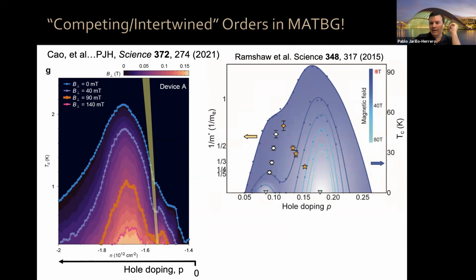In this case, they have to use gigantic magnetic fields, up to 80 Tesla, in order to measure this, but they basically saw a similar evolution with a small perturbation on the TC, which then isolates the 2 domes, and only one last remaining dome survives. Of course, the big difference between this data is that here the actual data points are those few discrete data points that you see here, okay? Whereas here, all of these data points are continuous measurements that we can take in this diagram, because we have full electronic control over our doping without the introduction of chemical impurities.